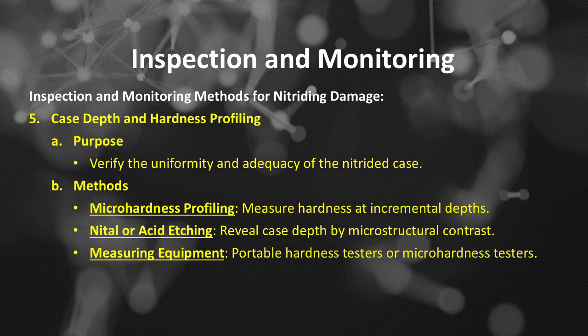Number 5 of the inspection and monitoring methods for nitriding damage is case depth and hardness profiling. Its purpose is to verify the uniformity and adequacy of the nitride case. Methods used are microhardness profiling, measuring hardness at incremental depths, and nital or acid etching, revealing case depth by microstructural contrast. Measuring equipment includes portable hardness testers or microhardness testers.